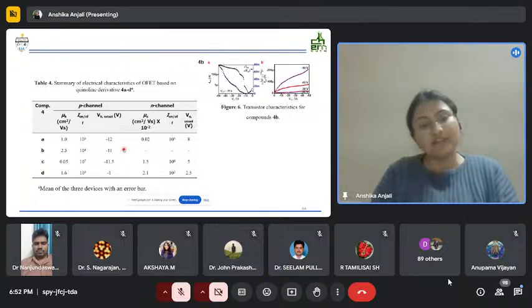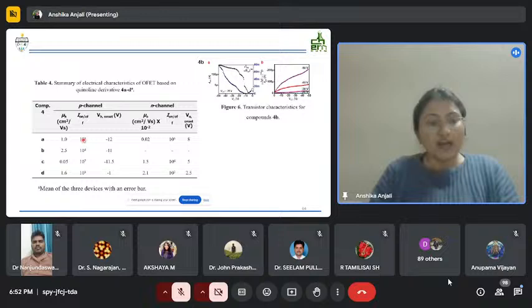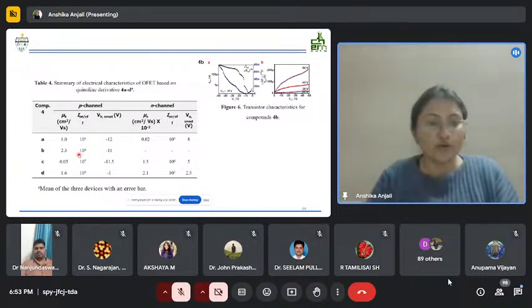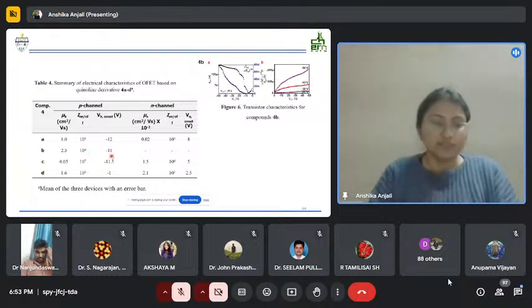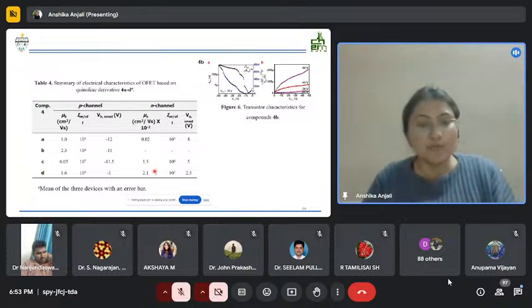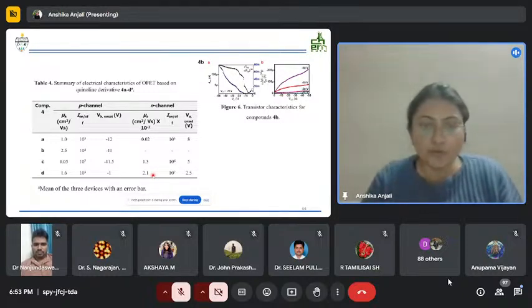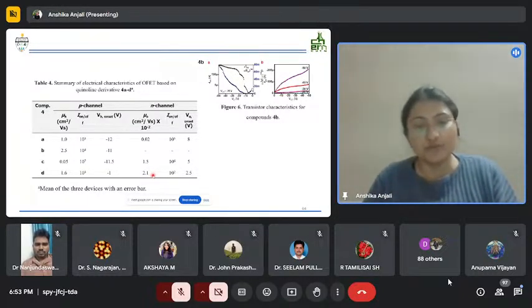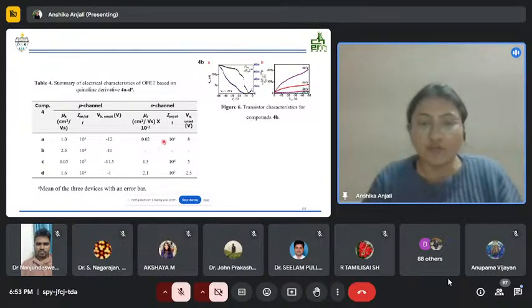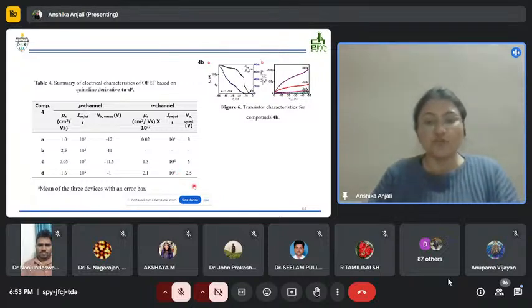Here, the 4-methoxyphenyl substituted compound exhibited only p-channel behavior, and the highest hole mobility was observed, 2.3 centimeter square per volt per second, with a current on-off ratio of 10 raised to power 4 and a minimum threshold voltage of -11. And the maximum electron mobility here was observed for compound d with biphenyl as our end groups, where an electron mobility of 0.002 centimeter square per volt per second was observed with a current on-off ratio of 10 raised to power 2 and a threshold voltage of 2.5.